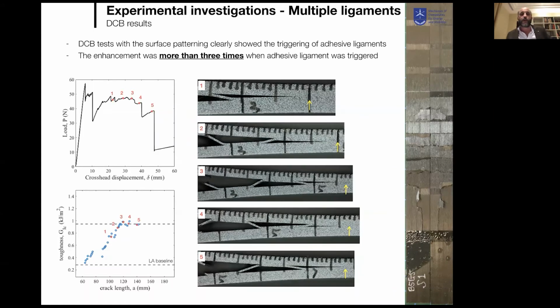So here you have some pictures of delamination. That means separation between substrates in composites that have been treated with special interfacial treatment. So you promote some mechanisms of failure, and especially the formation of ligaments at the interface during the secondary delamination. And you see that the effect of such heterogeneous treatment is to improve the toughness of the material by a ratio of 2 to 3. That means you get a huge improvement in the dissipation during the failure of your composite, only due to the introduction of this surface treatment, and especially with non-uniform surface treatment. So there is a huge direction of research here, perfectly in line with everything that has to do with additive technologies, because you can control this even more when you go to additive manufacturing.